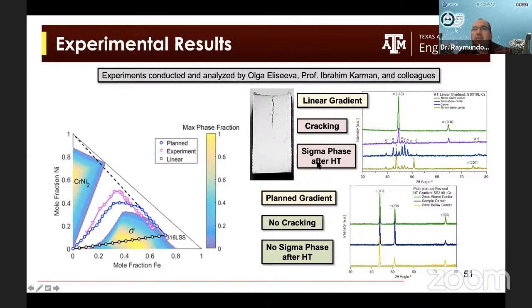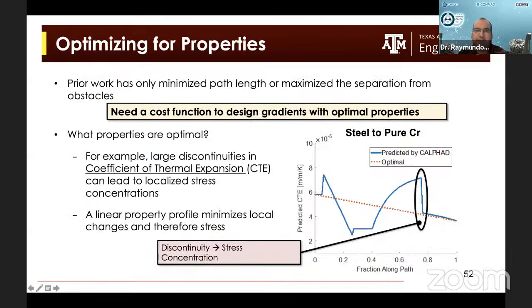And this is just a demonstration. The linear gradients has a lot of sigma phase. The planned gradient, on the other hand, we didn't observe any cracking. No sigma phase after we do heat treatment, as you can see here. So here we only have the alpha ferrite phase. Now, prior work by us was only minimizing the path length or maximize the separation from obstacles, but there are problems with properties.